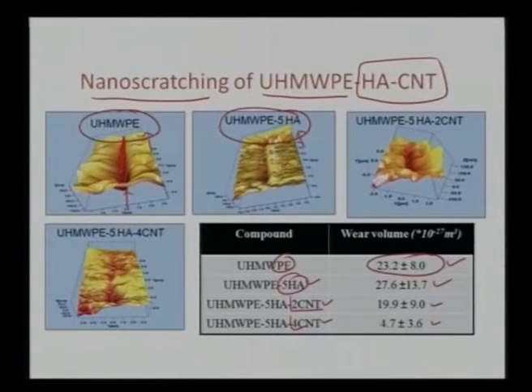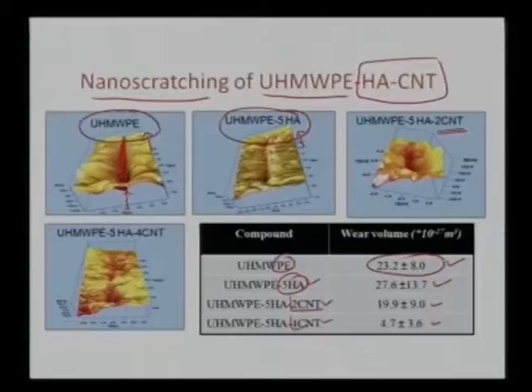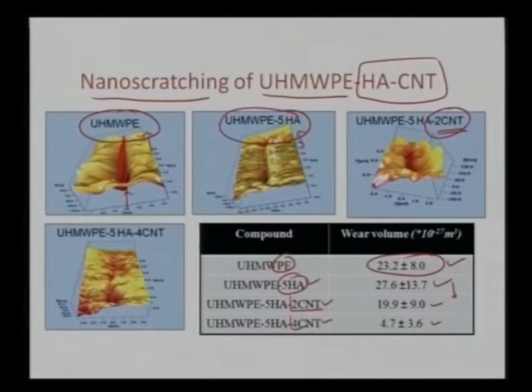This is happening because carbon nanotubes have very superior mechanical properties. They also serve as a lubricant. They have exceptionally superior wear properties, tribological properties, mechanical properties. At the same time, they have much more lubricating properties. So once I am introducing more carbon nanotubes out here, I am seeing an overall reduction in the wear volume. It means I am achieving a superior wear resistance in the CNT reinforced hydroxyapatite, which is again reinforced in a polyethylene matrix. So once I am increasing the CNT content, I am seeing a further decrease in the wear volume.